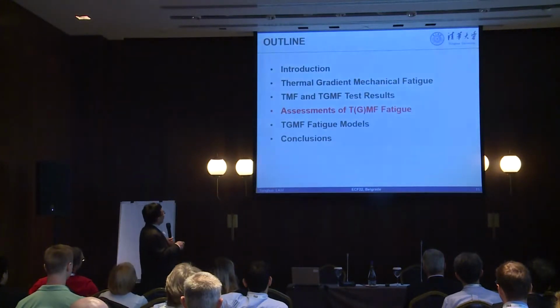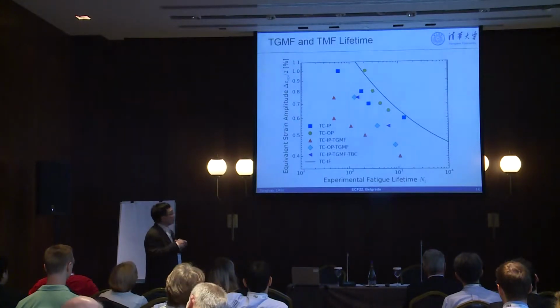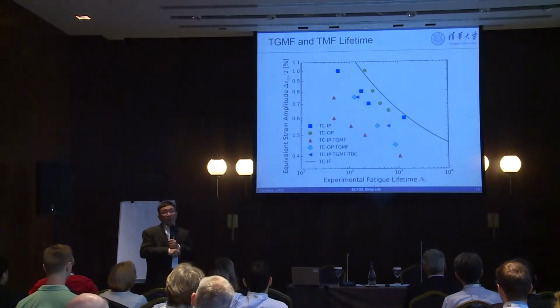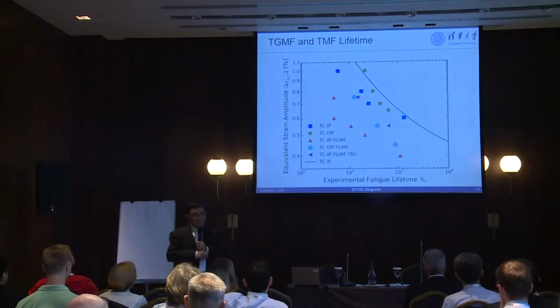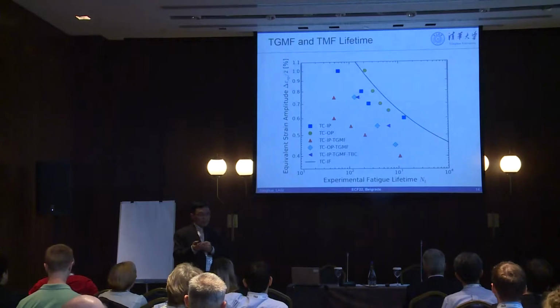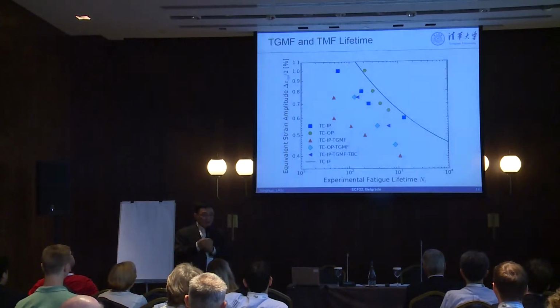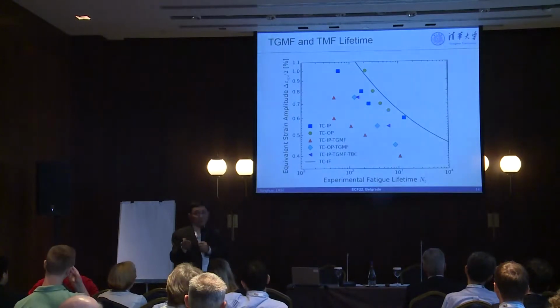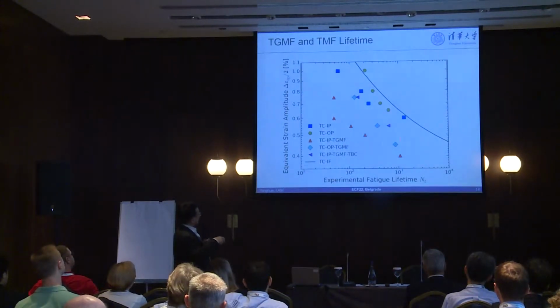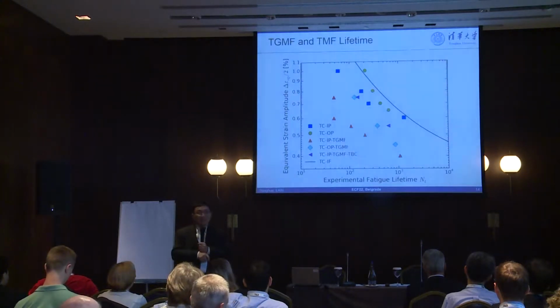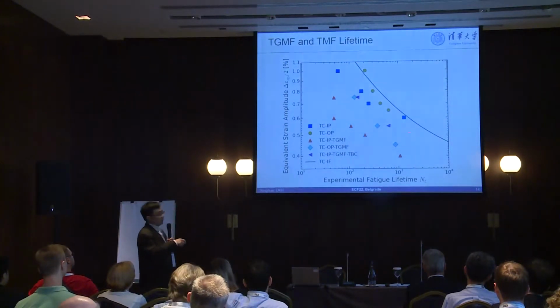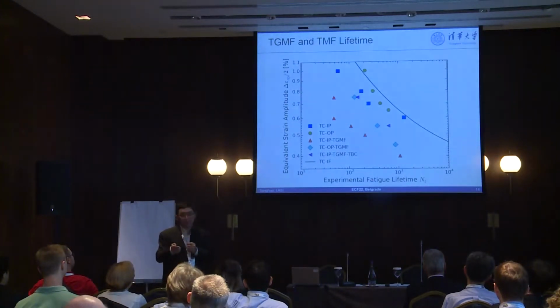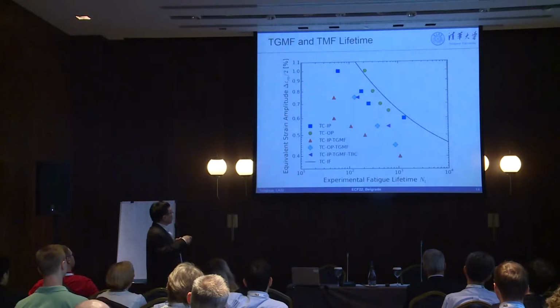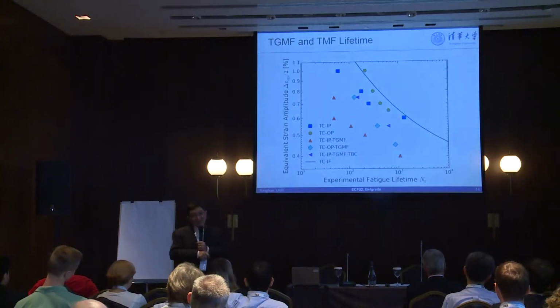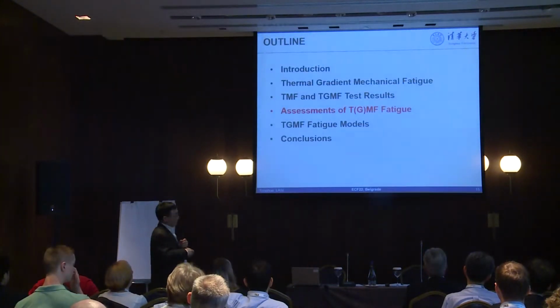Okay, and the question is how to bring all these experiments together. That's the point for us. The reason is that in reality we just know the temperature and the mechanical load in design, but the life assessment up to now just uses Arrhenius theory. We use this curve, but these results show you that this line is not conservative. It's very dangerous. The difference comes up to 2 decades. Therefore, the design becomes nonsense. Therefore, the question is how to quantify the thermomechanical or thermal gradient mechanical effects in your life prediction.